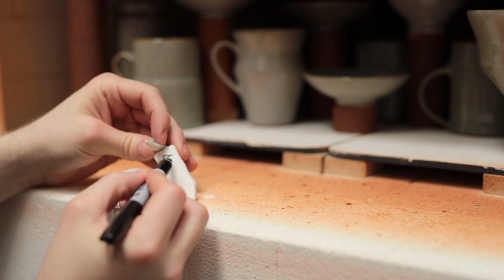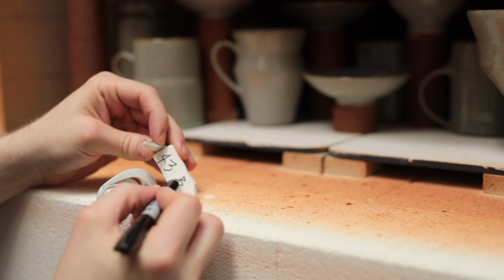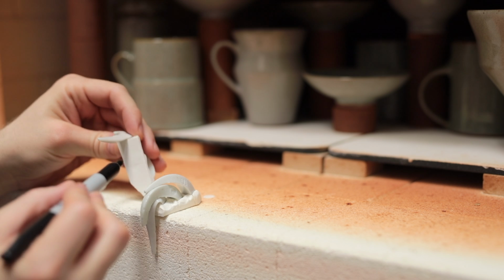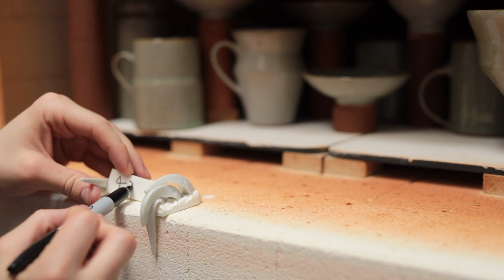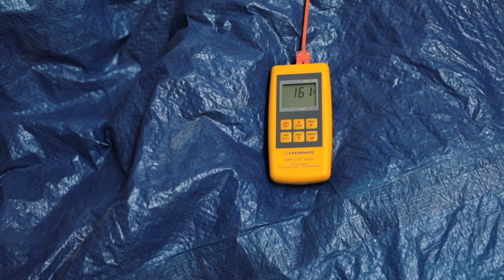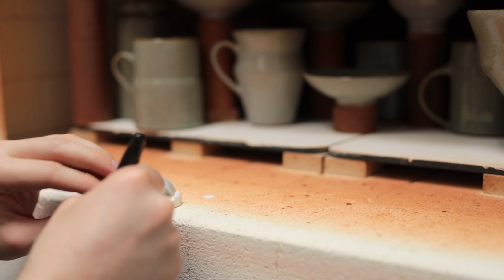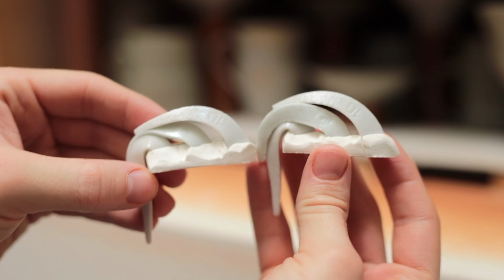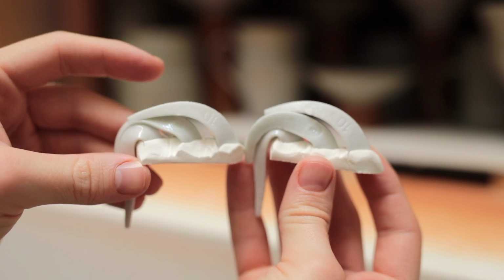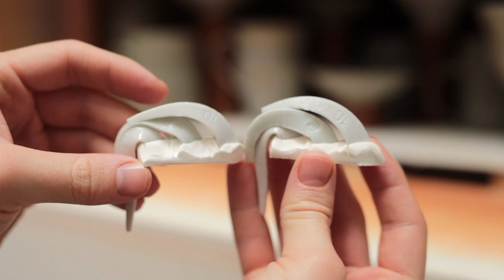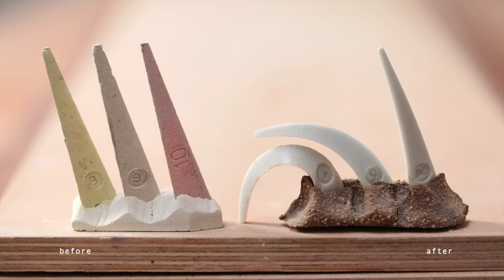These are the pyrometric cones from the top and bottom, which during the firing are viewable through the spy holes in the door. As opposed to measuring straight up and down temperature like the pyrometer does, these measure heat work, which is heat over time. Each of these cone packs has cone 8, 9 and 10, and these melt and bend over, measuring very specific temperature ranges. And it's really these which I'm looking at to know when the firing is truly over. Clay and glazes need to mature at certain temperatures for longer periods of time. And the analogy I like to use is to think of it like baking a cake.